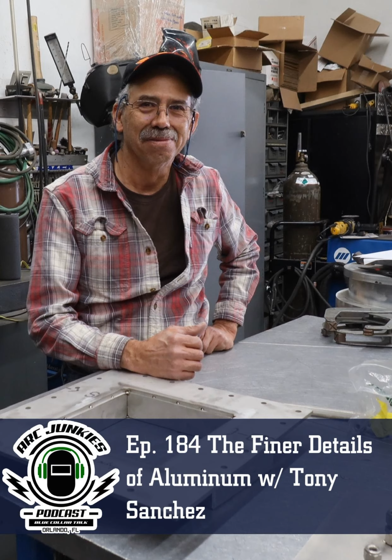Then I polish it till there's no grain in it, so it's nice, almost like chrome. And if you get it angled right, I can take a weld, let's say a MIG gun weld or a TIG weld, and rip that thing out almost as fast as I put it in with an air chipper. Huh. It's just like an air arc in reverse, and it just slivers it right off. And what I've learned over the years, because I've had to weld a lot of things together just to hold them together to start welding somewhere else, is you learn a lot because as that air chipper is coming out, you can see where it's fracturing and where pinholes are up on corners and stuff. So it's a learning curve.